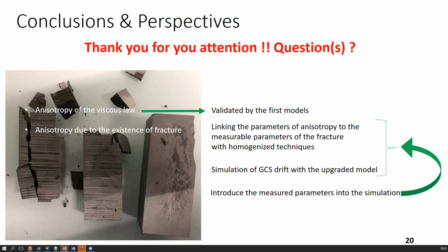Actually, we are willing to understand the creep slip on the fracture with the hypothesis that I've already made for the homogenization. We assumed that the behavior was a Lemaitre creep law. So if so, we would like to measure the parameters of the Lemaitre creep law, but actually there is no certainty that this assumption is true. So the first step is to just try to understand or see the behavior of a fracture, and then maybe identify the parameters of the law.